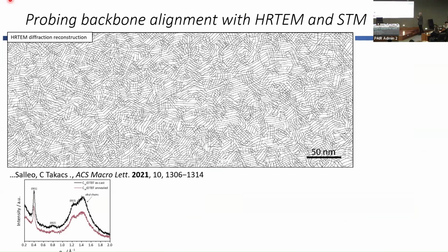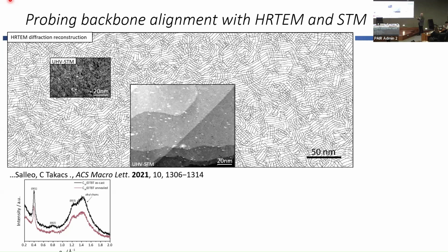We then looked at this further by high-resolution TEM, done by the Salleo group at Stanford. And in this case, they're taking a reconstruction. So this is not an image. This is a reconstruction of an image. And you can see that the lines are the polymer backbones. And one thing that came out of this was the crossing points. So there was a lot of crossing at almost 90-degree angle between the backbones. And there was very little parallel arrangement at short length scales. Almost all were the same angle.